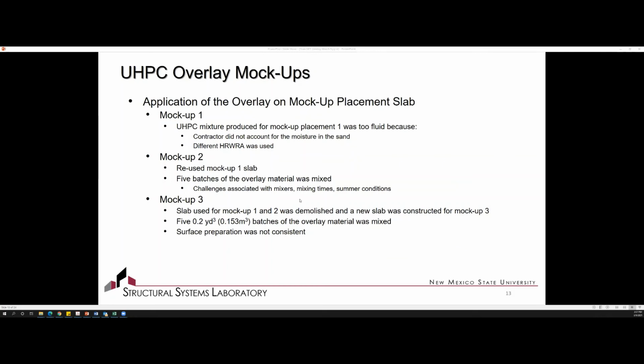The moisture content in the sand was not properly accounted for. And then a different superplasticizer was used than what was specified. So we actually didn't get set for about 7 days with this product. So we immediately knew that we had to do something else with this. So for mock-up 2, we reused the mock-up 1 slab. We didn't really place the UHPC on that, just because we knew issues were already there.